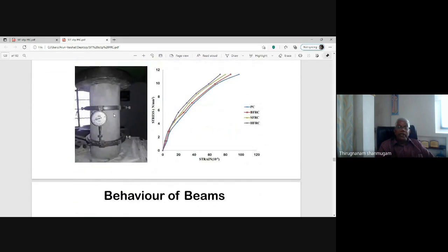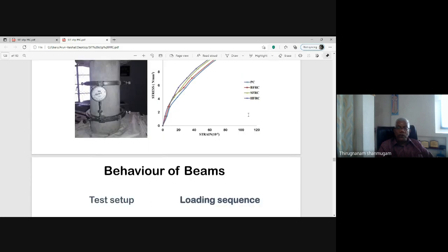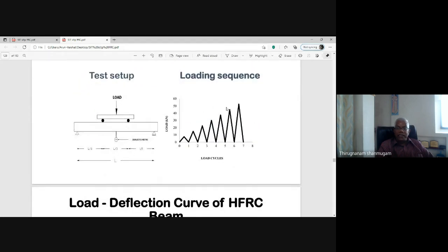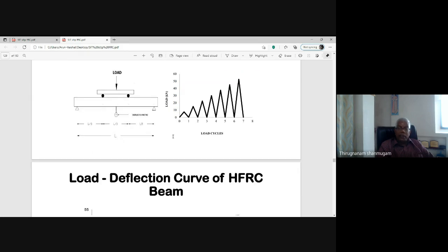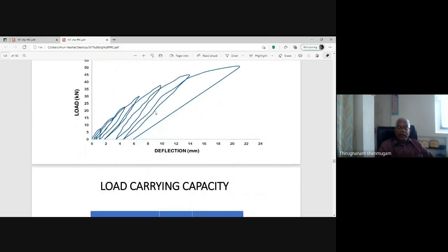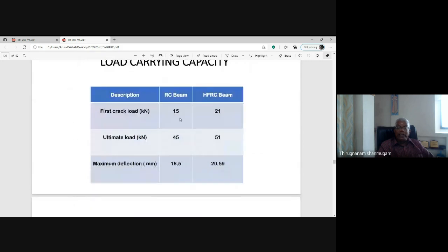So the stress strain behavior of the concrete cylinder and FRC cylinder is like this. It gives the modulus of elasticity values. In the beam testing, here only the monitoring forward cyclic loading is adopted, not the reverse cyclic loading. The load deflection behavior: load carrying capacity is 15 kilonewton as the first crack load for the RCC beam. When the fibers are added, 21 kilonewton, just a 40% increase in the load carrying capacity.